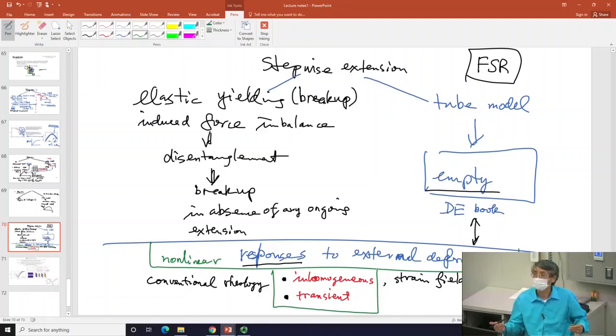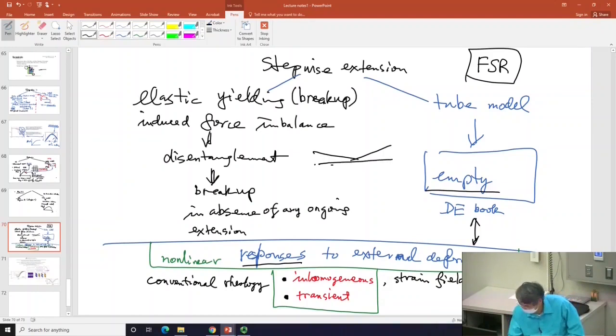So-called shear thinning, we can speak about it. We even covered that part of it by superimposing some step strain or oscillatory shear to learn about the nature of steady state. Only in shear you can achieve steady state, but even that steady state is difficult to achieve, generally speaking, and impossible to achieve for melts, because we don't have a device that is free of meniscus.